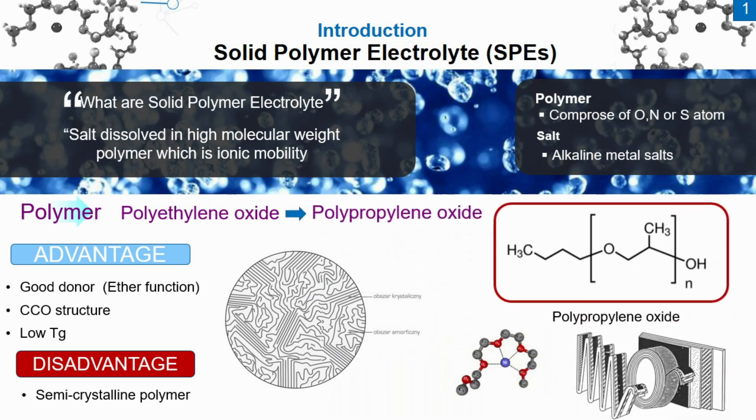Our plan is to improve ionic conductivity by plasticization to destruct the PEO crystal and increase amorphous phase. As polypropylene oxide or PPO has quite similar structure with PEO but is 100% amorphous, it's possible to use PPO as plasticizer. We then intend to study further about the molecular characteristics and material properties of PPO based on molecular simulation techniques.